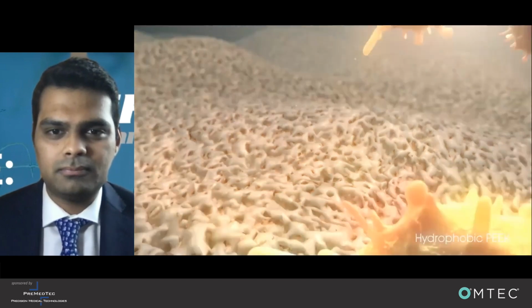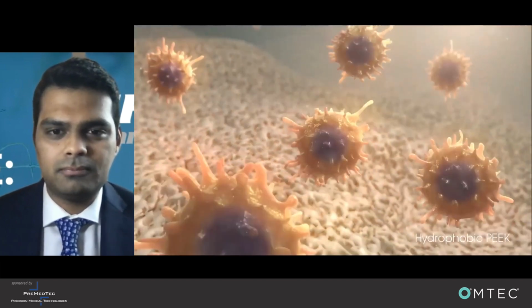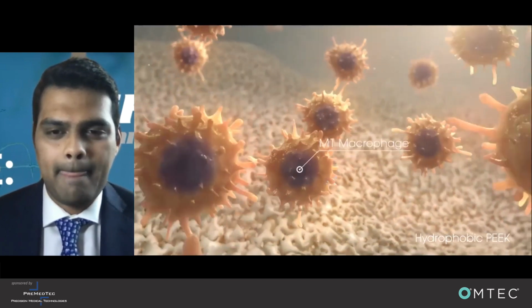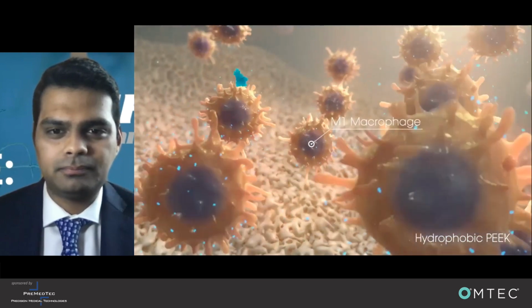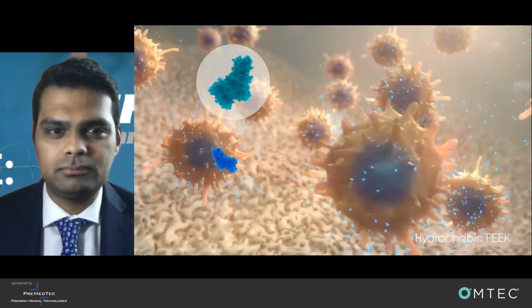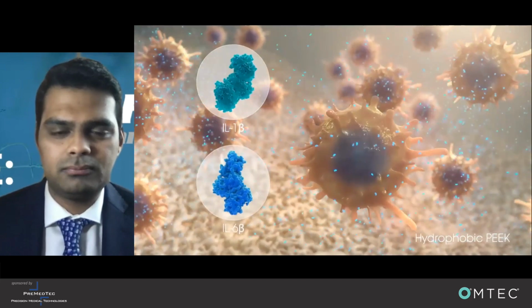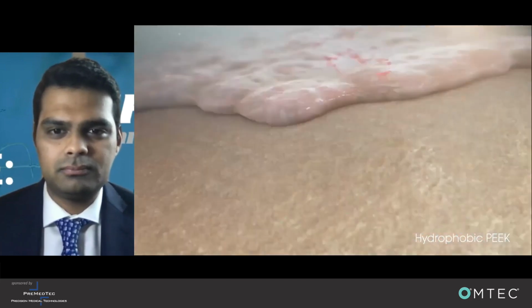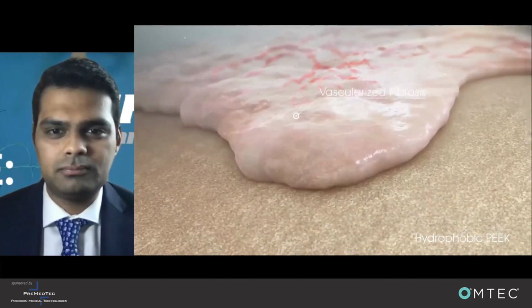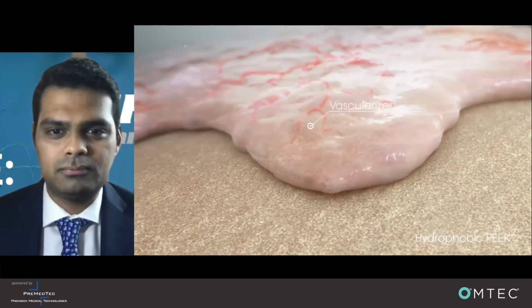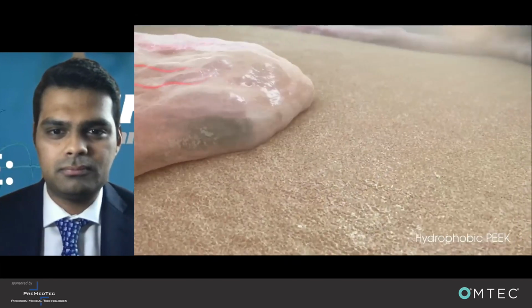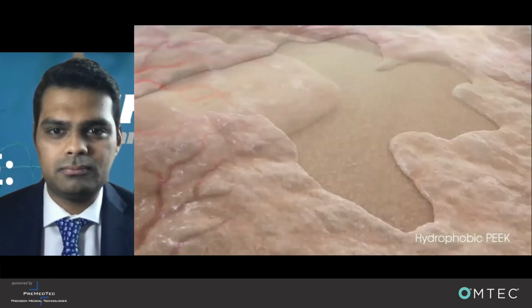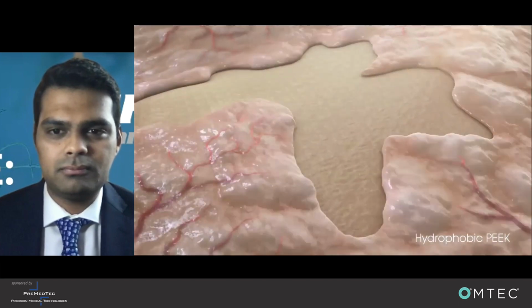Contrarily, the inert hydrophobic surface of PEEK demonstrated a prolonged M1 inflammatory response, along with protracted increases in IL-1 beta and IL-6 cytokines, which are known to contribute to vascularized fibrosis, or walling off of a foreign body or implant, deemed to be not self or dangerous to the immune system because of its hydrophobic nature.